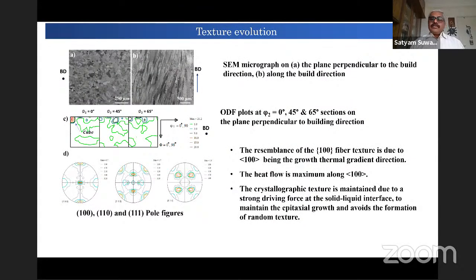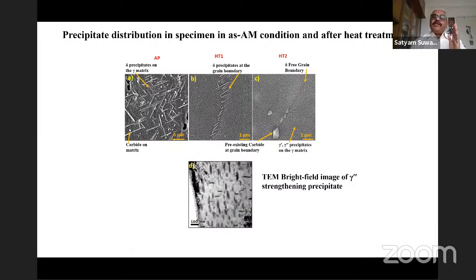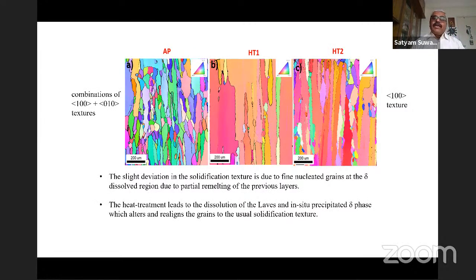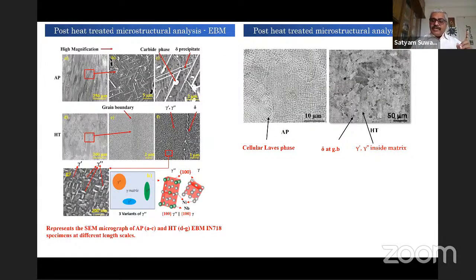Now, considering the texture evolution of these processes, we have seen that in the EBM condition we get a perfect cube texture, and this paves the way for a very important thing. One important aspect is the precipitate segregation at a grain boundary, as we have seen here. But the most important aspect is the possibility of going towards a feature similar to single crystal or directional solidification type. We could see here, and I will show you this in a short while, how this has helped us. And of course, similar heat treatment leads to different kinds of phase stabilities in this condition.